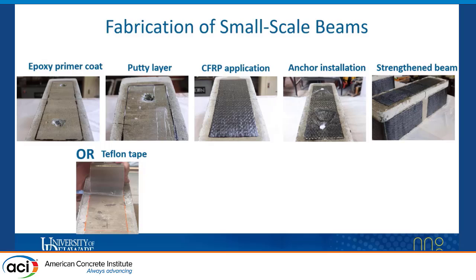As for the strengthening of the beams, the concrete surface was prepared with a coat of epoxy as well as a coat of putty. However, that's for the bonded group. In the case of an unbonded beam, those 2 coats or primers were skipped and a bond breaker was applied, which in this study was a sheet of Teflon tape. Following that, the carbon fiber was saturated using the epoxy and the CFRP was applied to the tensile face. Then the anchors were embedded into their anchor holes, the anchor splays were fanned out over the CFRP, and lastly, the shear wraps were applied around the sides of the beams, and a square CFRP patch was placed over the anchors.